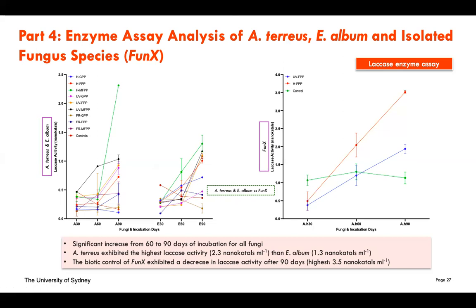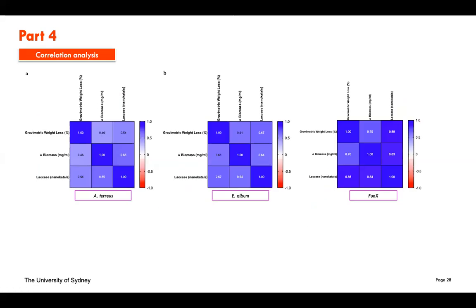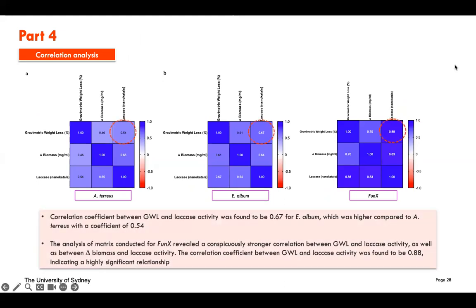So we assume that this laccase enzyme contributed more. That's why the weight loss for the new isolate is much more compared to the previous fungi. Right? And then we also did a correlation analysis to see the relationship between the weight loss and the laccase activities. You can see the ones that are circled, especially for the new isolate, the relationship between weight loss and the laccase activity is the highest compared to E. album and also Aspergillus terreus.